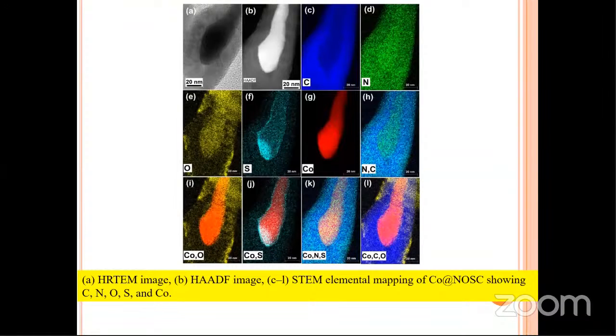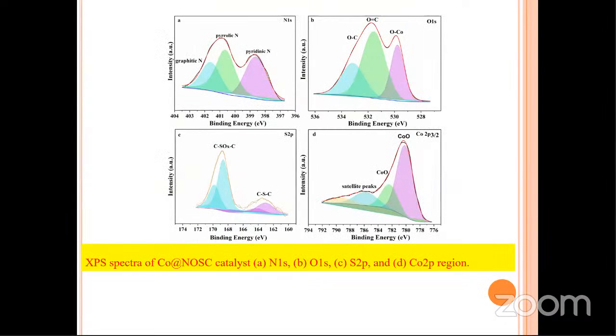Here you can see the nice picture from HRTEM, which shows how the cobalt is coated. In the first image, you can see that normal carbon has the blue color. You cannot see the cobalt moiety. The second one is nitrogen. From here, you can see that cobalt, shown in red color, is coated with nitrogen, carbon, sulfur, and oxygen. The presence of all the groups like pyridinic nitrogen and pyrrolic nitrogen was further confirmed by XPS analysis.